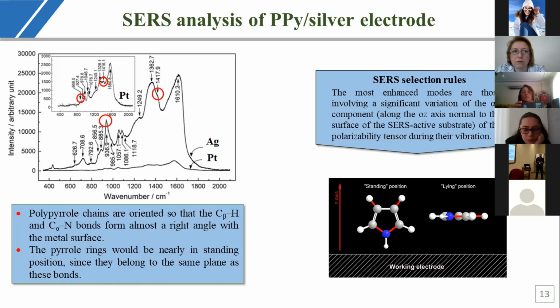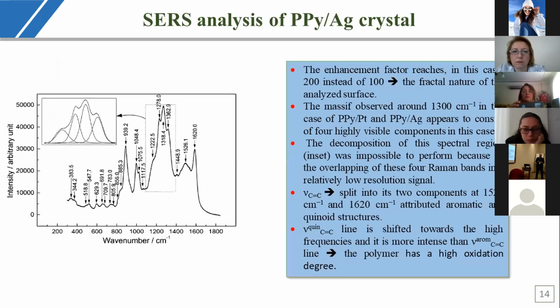The same spectrum of polypyrrole obtained photochemically with the deposition of silver on a copper plate is presented in this figure. In this case, the enhancement factor reached 200 instead of 100 for the first case. This huge exaltation is due to the fractal nature of the analyzed surface, according to some published work. All the peaks are highly resolved, and the massive observed at